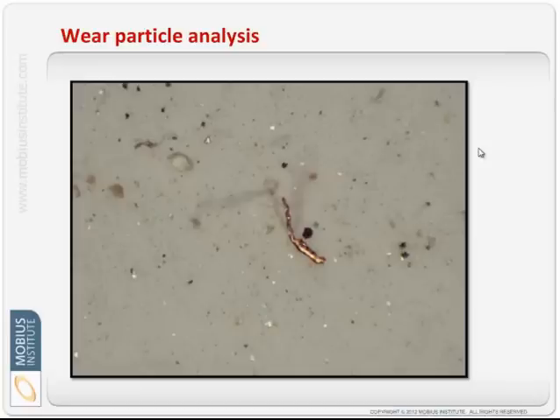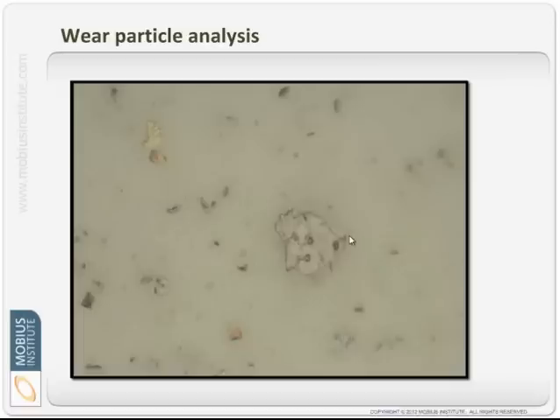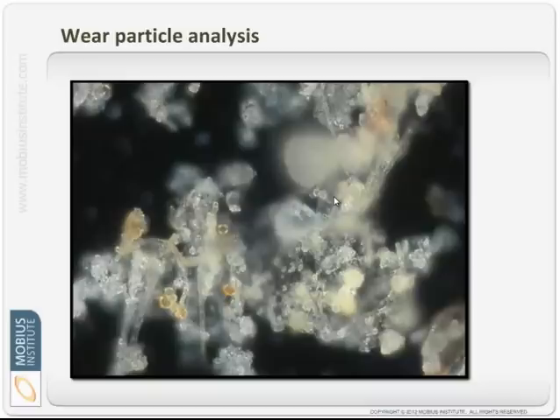If we perform wear particle analysis, we can actually look closely under a microscope at the lubricant to see if there are signs of wear. Now, large particles like this allow an analyst to determine the type of metal and the nature of the wear that's taking place. Cutting wear and other sorts of wear that have characteristic shapes and colours. So a trained eye can tell what sort of particle that is, and because of its shape, how that particle came to be, whether it's been rolled through by the bearings, whether there was skidding involved, whether there was heat involved, and so on. So these sorts of techniques can also test if there's dirt, in effect, silicates in the lubricant.